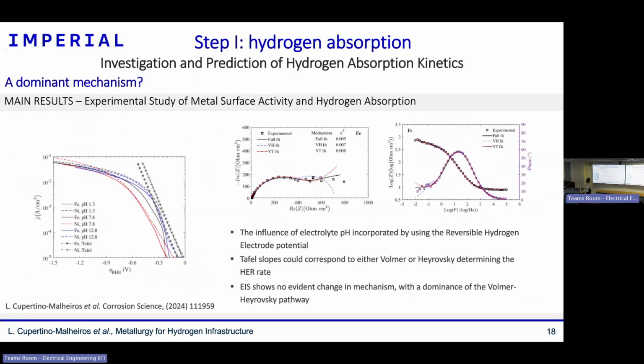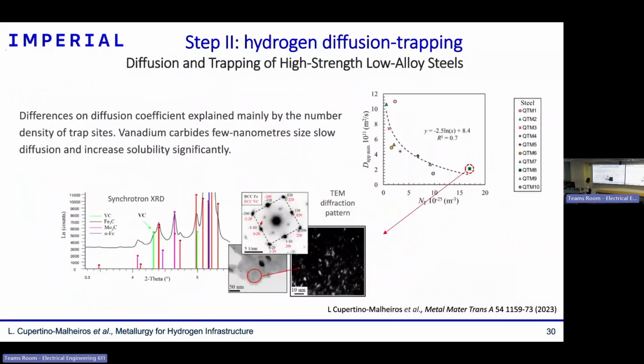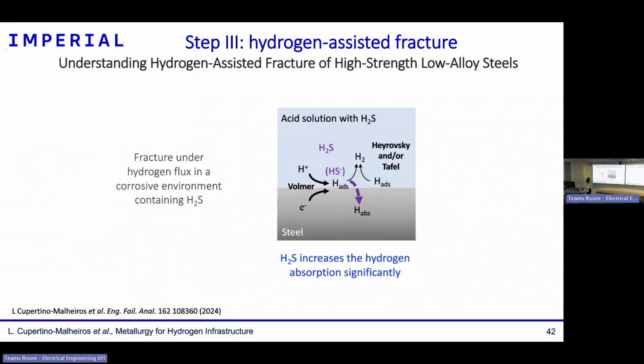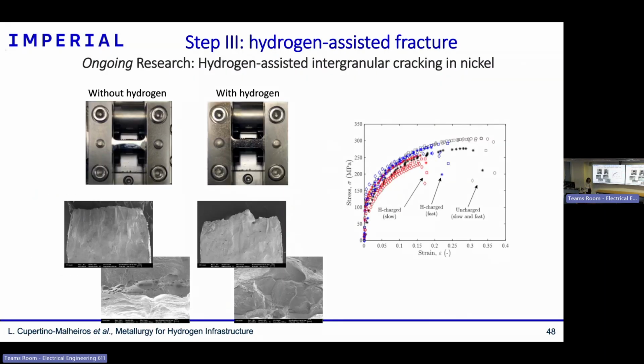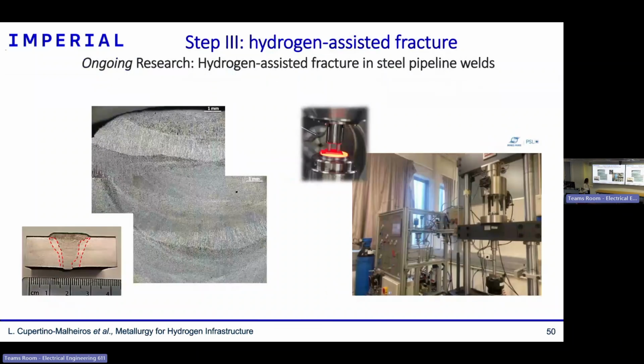I mean, I'm not working with methods. So the way we are currently doing it is going for smaller samples, both for mechanical testing and for hydrogen diffusion and concentration. So we can extract samples in different areas of the welds, characterize the microstructure, and here what's illustrated is a TDS, thermal desorption spectroscopy, a way to measure the hydrogen that's absorbed and also get parameters of trapping and diffusion. So what has been done in this study is really taking samples from different areas of the welds and then doing the diffusion and trapping with permeation and TDS tests with smaller scale samples, in different zones.